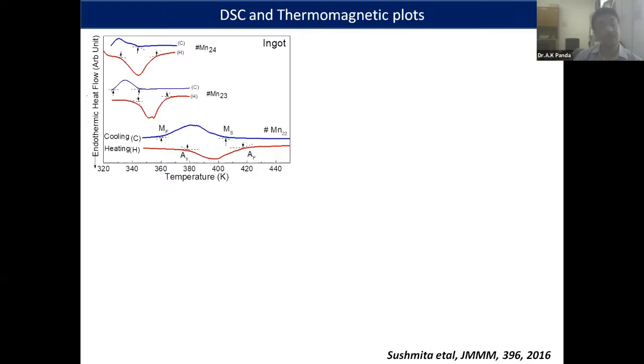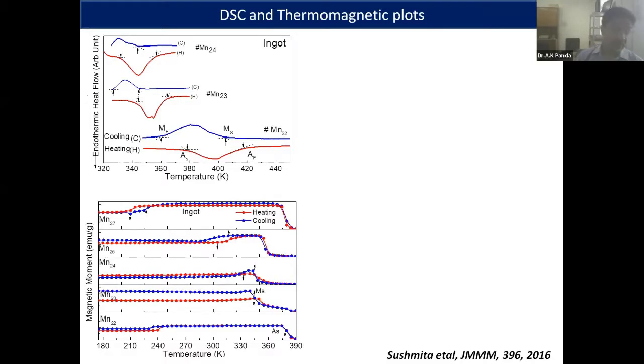So what it means is that we have more austenite available at room temperature. This is exactly what we have seen when we have done the X-ray diffractions. And these are the magnetization plots, thermomagnetic plots rather. This is the change of magnetization with respect to temperature, measured using a vibrating sample magnetometer.